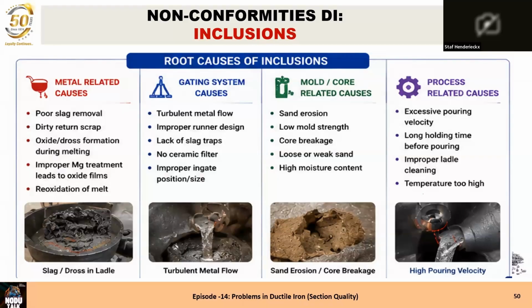The process-related causes: excessive pouring velocity. The metal should never enter the casting with 1 meter per second. Never. And the lower, the better. Even the biggest castings are poured with a metal entering speed of less than 1 meter per second. Long holding times before pouring. Of course, the longer you are waiting there, the magnesium is still reacting, and magnesium reacts with oxygen from all over, and eventually with slag, and gives then the inclusion. Improper ladle cleaning.